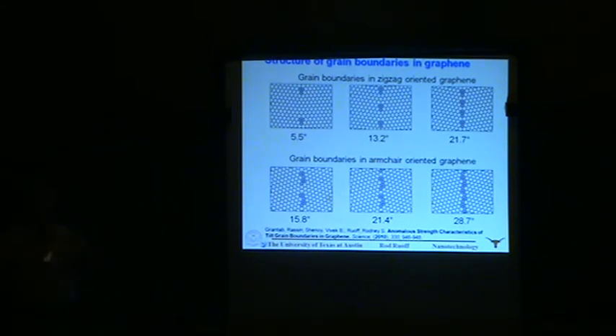But I think I want to leave you with a bigger picture: if we can get significant bonding along grain boundaries, rather than just missing bonds entirely, then we're going to be in good shape in terms of strength. I told you that graphite can be a very strong material, but only at the single crystal level. In graphite, the grains just kind of butt up against each other. There's no covalent bonding at all. Or they subtend, something like plate tectonics, and then there's just van der Waals. So the individual crystals, the grains in graphite, are remarkably strong, about 130 GPa, but graphite as a material is ridiculously weak. It's in the megapascal regime rather than gigapascal.